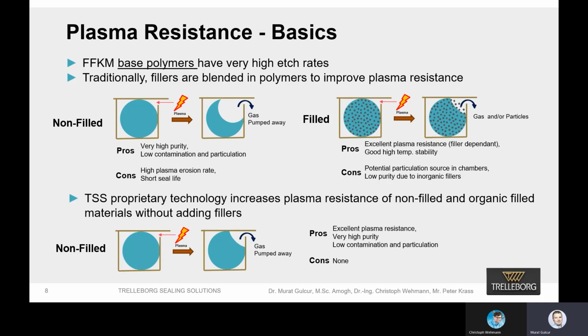So let's talk about the plasma resistance. So the basics. Obviously, the most basic ingredient of an elastomer formulation is the base polymer. So if you specifically talk about FFKM based polymers, obviously they are fully organic materials. Therefore, their etch rates, their plasma resistance is very low, especially when we talk about ion bombardment type of plasma. And traditionally, fillers are blended in these base polymers to create elastomer formulations, elastomer compounds, which will have improved plasma resistance because of the plasma resistance of fillers.